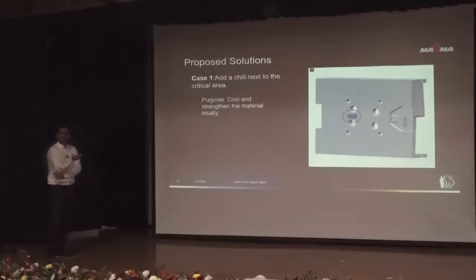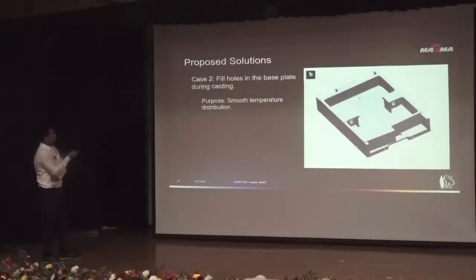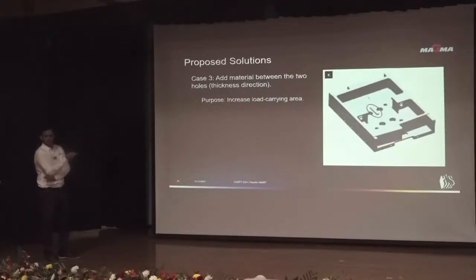We prepared 3 designs with different methoding and a few process changes. In the first case, we put a chill between those holes to speed up the cooling rate of that region. Second, we filled those holes and would machine the holes later. And in the third case, we increased the load carrying area, adding some extra metal to it. So what would be the best result? We will see.